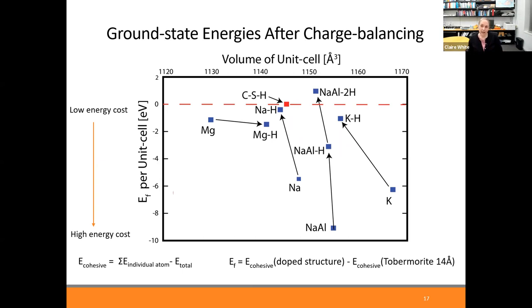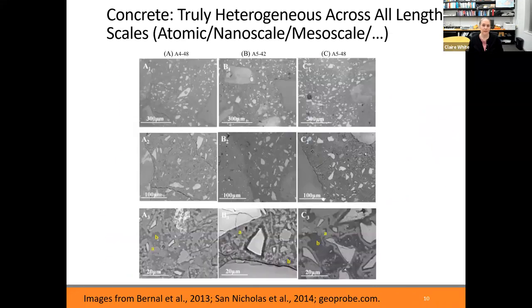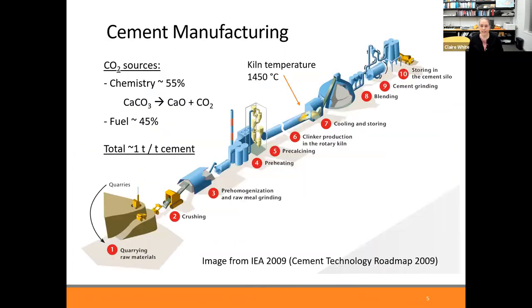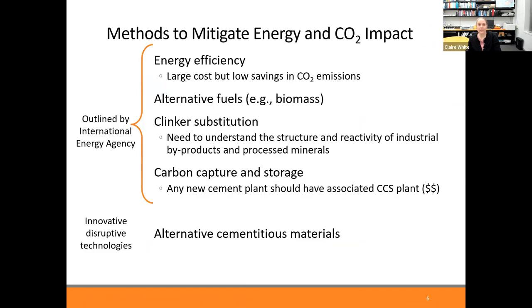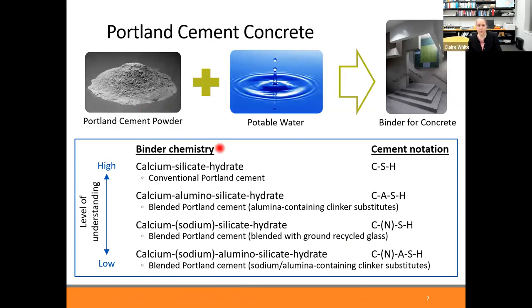There's a question that's popped up on the chat, and the question is, are these gels the clinker? They are not. So to describe what clinker is, because I assume that not everyone knows what clinker is, if we go back to this slide here, what comes out of the kiln is actually called clinker. And then that gets blended with gypsum to make Portland cement powder. And then you mix Portland cement powder with water, and that's when the CSH gel forms. So this CSH gel is what's known as a hydration product when you mix the cement powder with water.